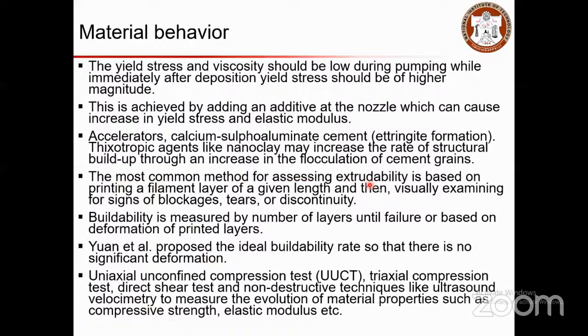The most common method for assessing extrudability is based on printing a filament layer. In that case, you can visually examine the layers as well. Is there any sign of blockage or tears or discontinuity? The buildability depends on the number of layers that you construct for the printed formation.